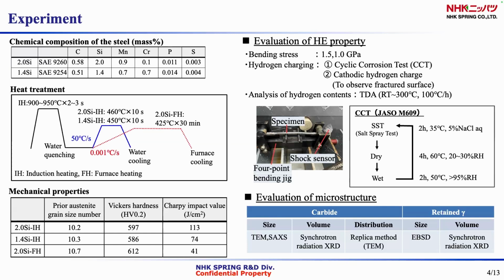Although the grain size and hardness were the same, the Charpy impact value tended to be highest for 2 silicon IH steel. In order to evaluate the hydrogen embrittlement properties, a 4-point bending test was conducted under cyclic corrosion test. The fracture life was measured by detecting the electrical signal output when the specimen fractured. And the cathodic hydrogen charging test was also conducted, with fracture surface observation. The size and volume of carbides and retained austenite were measured using X-ray, synchrotron radiation, replica method, and EBSD.